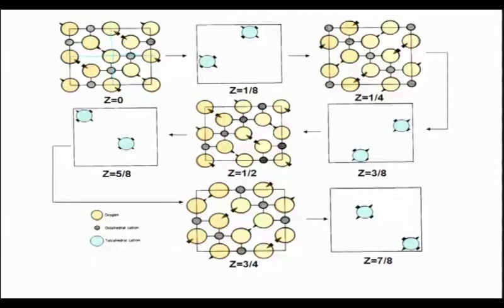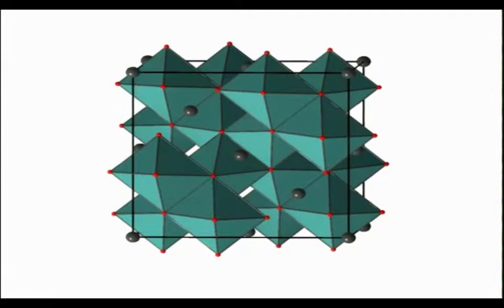so as to achieve a unit cell which is periodic in nature, which is repeatable in nature. Okay. So this is a complicated lattice. You have to go layer by layer filling of cations in the anion lattice, and this will make a big unit cell of spinel structure. So this is how it's going to look when you make it.